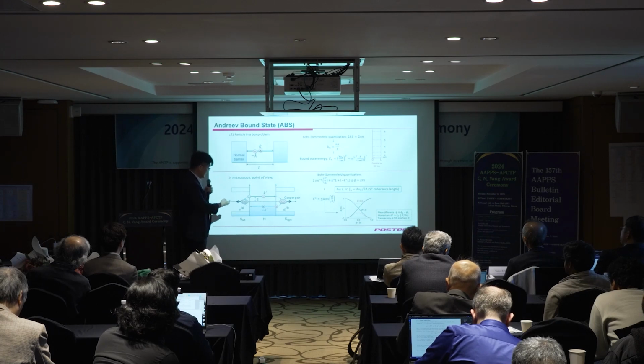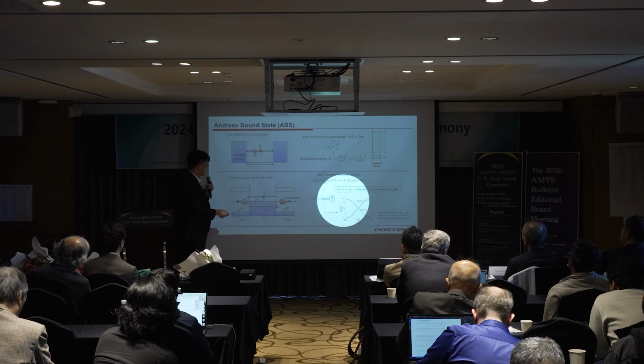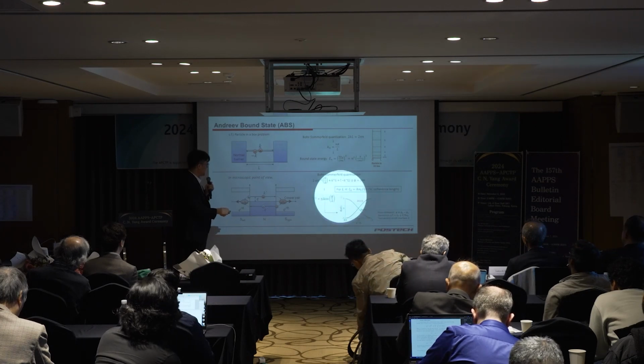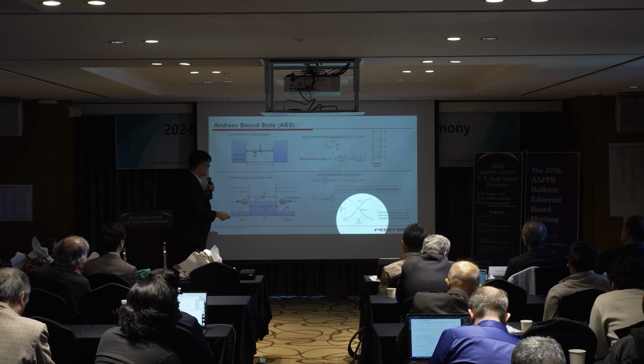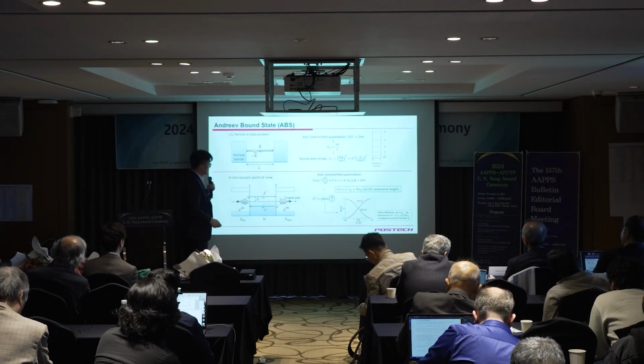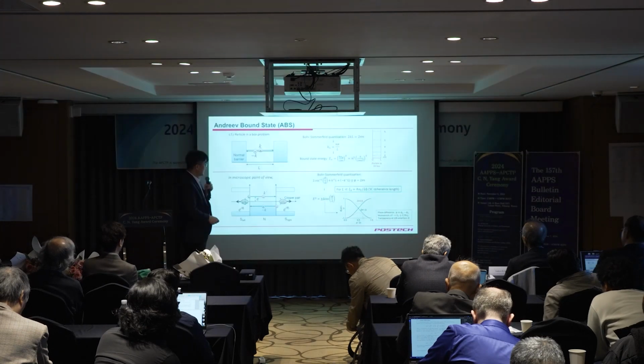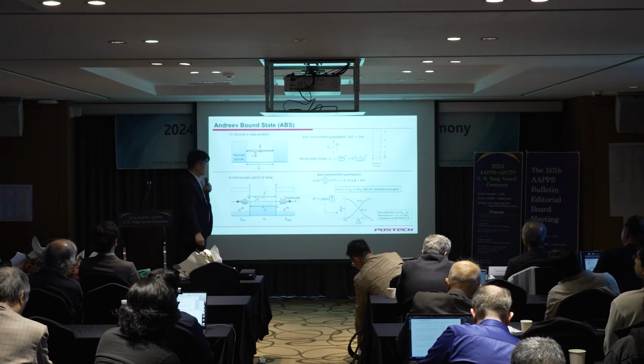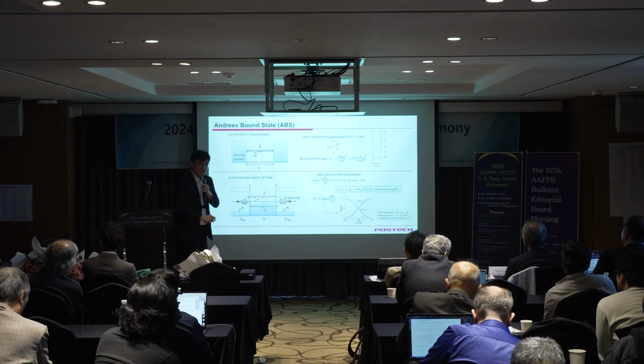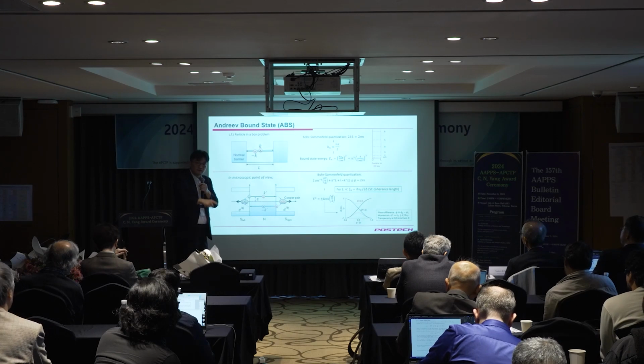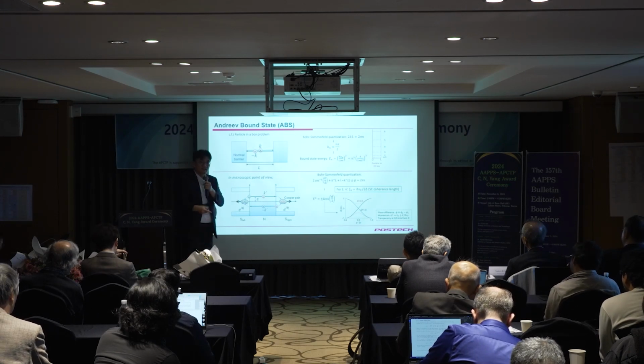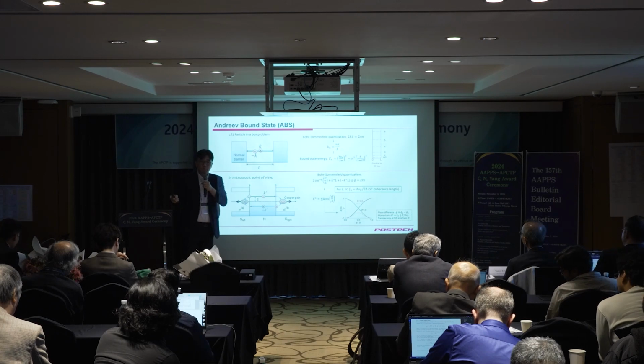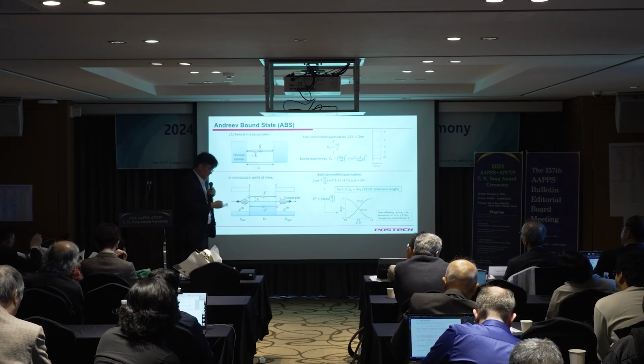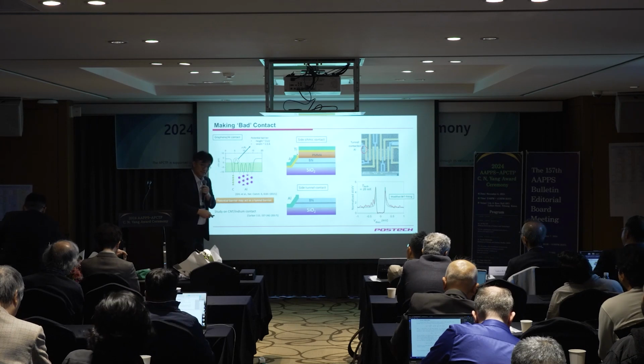And this bound state has a phase-dependent spectrum. The energy is bounded by the superconducting gap, and it is a function of the phase difference between these two superconductors. So we can take this as a kind of artificial band structure of a 1D material. Although this is not a real material, energy disperses as a function of phase difference. The phase difference phi acts as a quasi-momentum in a real condensed matter system. That's basically our system.